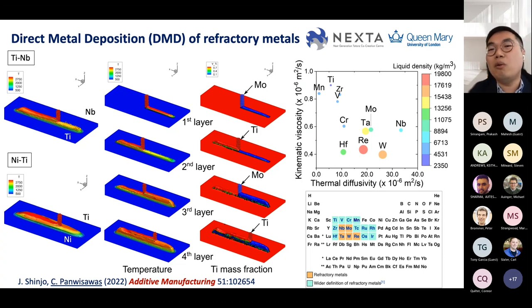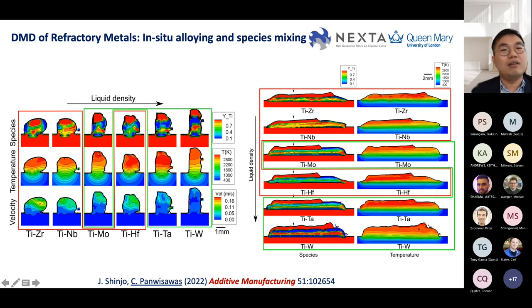Why doesn't it work from a thermal chemical fluid point of view? We can have some explanation on that. That's because of, for example, we are looking at the same map, viscosity versus diffusivity, but we now focus on the refractory metal. We can see from the next slide that there is some trend that some heavy liquid density doesn't mix very well at this process condition. You will see tungsten make it nearly a laminated structure compared with titanium niobium or titanium zirconium. And this is why some of the application using tungsten additives doesn't mix very well. But anyway, we can use this kind of simulation to explore even further how can we improve this mixing.